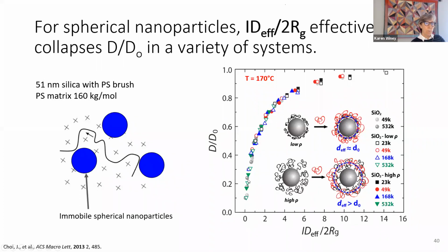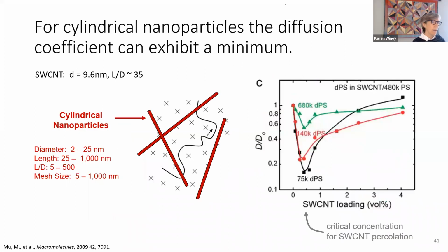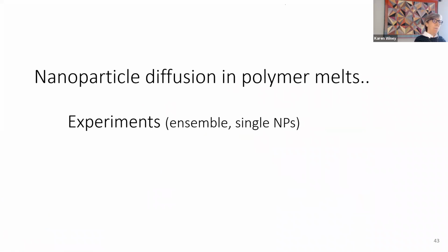And so big drop in diffusion coefficient, as much as a factor of 10. And then way out here, ID over 2RG of 14, and we're still not quite back to bulk. And that, I think, is the puzzling piece, that so few particles can still somehow slow the polymer diffusion down. These are all in athermal systems at 170 degrees C, and we have a weakly adsorbing material that also showed the same trend. So, I'm going to skip the stuff about cylinders because I just want to say quickly something about nanoparticle diffusion.